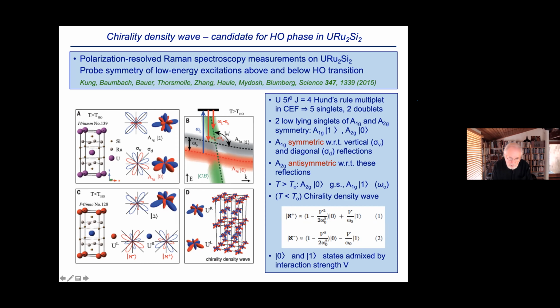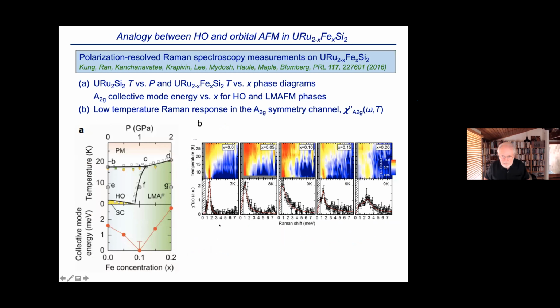And then they've also looked at the iron substituted materials that we prepared. And so there's an energy associated with the formation of this ground state, or this chirality density wave ground state candidate for hidden order. And so this occurs at about 1.5 millielectronvolts for the pure compound. And then as you add iron, this thing decreases and vanishes in the neighborhood of where the transition was supposed to occur. And then it reemerges on this side. And that's shown in these data right here. These are the low temperature Raman response in the A2g symmetry channel.